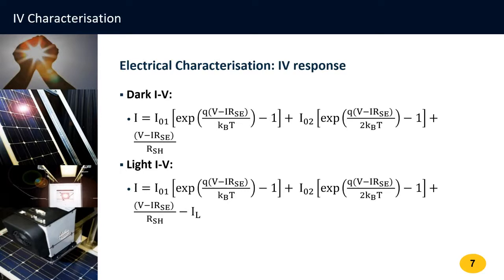However, as we'll see later on, there is a module that does not exhibit typical IV characteristics, and when you apply this, it wouldn't be able to fit unless you included a variable ideality factor where it came out to being less than 1, which according to physics is not possible, at least for this sort of module. And obviously that doesn't make sense, and we want to be able to make sense of what's going on. It's kind of the point of this sort of characterization.